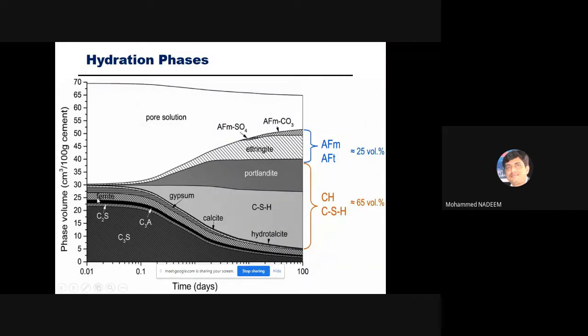Phase we discuss. If you see, these are the 4 major components. This is the water, and slowly, over a number of days, these 4 components along with water are converted towards the CSH. Portlandite is nothing but calcium hydroxide, and ettringite is a calcium sulfoaluminate component. At the end of 100 days, your concrete looks like this. So we want to utilize this portlandite and a certain percentage of pores.